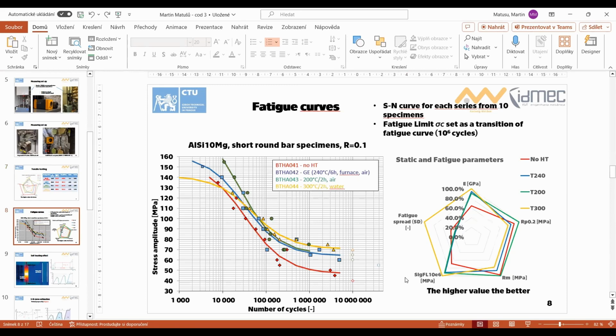To point out the fatigue curves, as you can see on the left side, I would like to say that all the heat treatments obviously bring better results in the fatigue curves department. We are using the Kohout-Věchet regression, which quite well represents the transition from the low cycle fatigue to the high cycle fatigue. Also, the runout condition for the specimen was aimed at 10 million cycles.